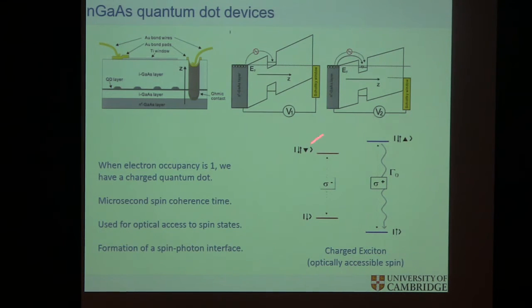And once you have that, of course, you have these 4-level systems. So that, for us, brings us to the atomic type approach, and then we don't have to worry about the rest of it until we get a polariton coherence or something. But the main thing is the ground state is spin up and spin down, for the electron that is trapped in this configuration, and the excited state is that electron plus an extra exciton, the whole thing is called a trion. And you have spin selective transitions.